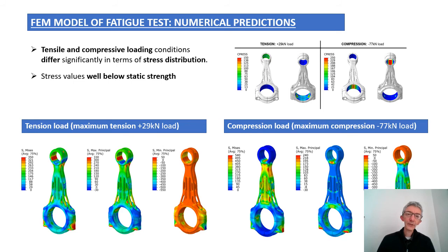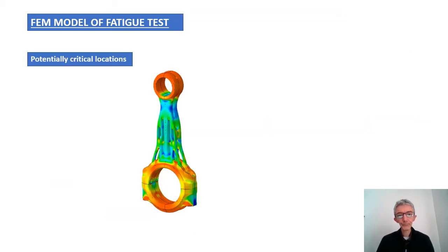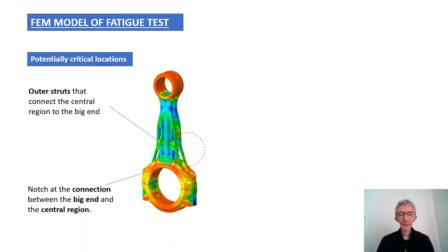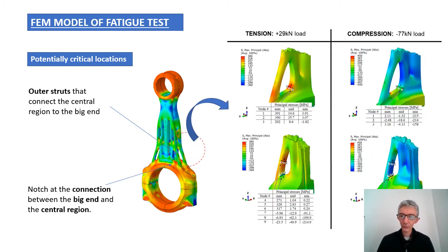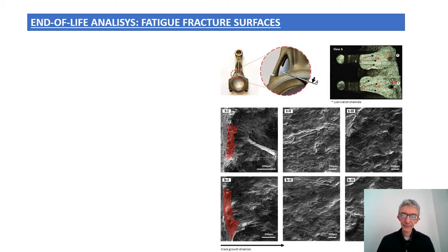In general, the stress values remained well below the static strength, but at the moment, it is not yet possible to make a comparison with fatigue strength data, since these were not yet available. Nevertheless, the finite element model allowed the identification of potentially critical locations, especially in the outer struts and at the connection between the big end and the central region. So in this area, we carried out more detailed analysis.